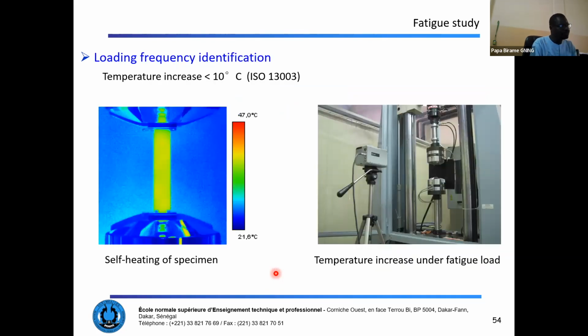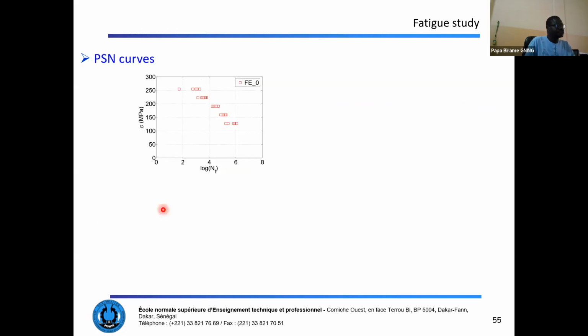So we can see that flax fiber composites have stable behavior and a small self-heating during the fatigue loading, and the glass-based specimen has regular heating during the fatigue loading.